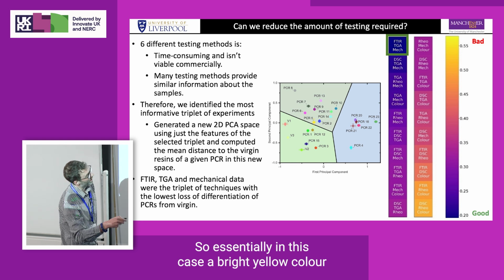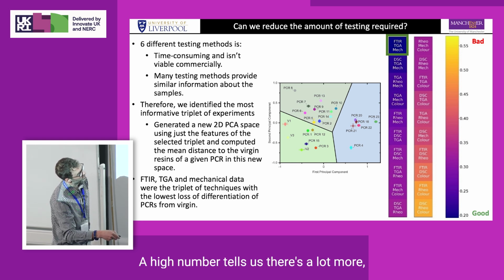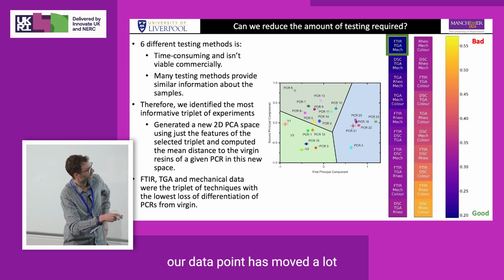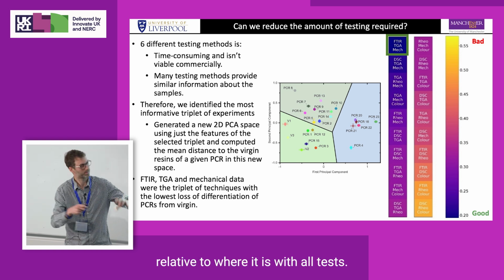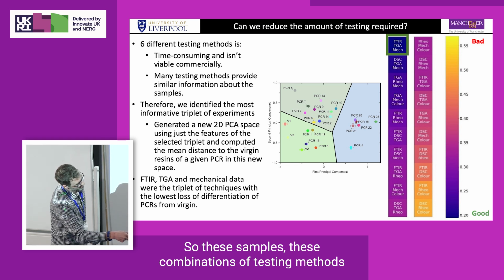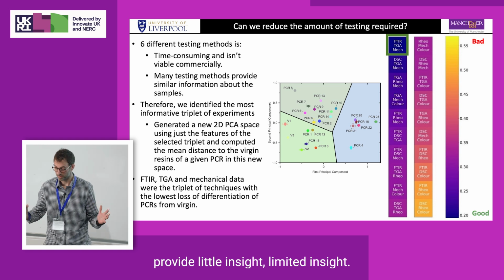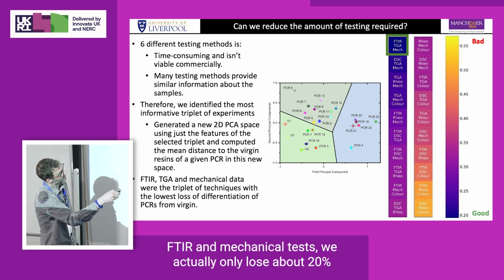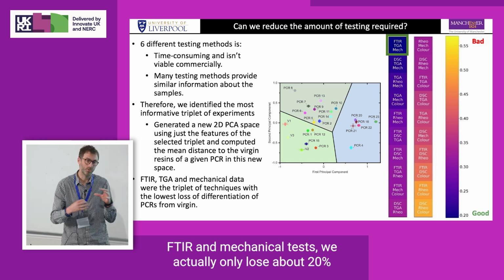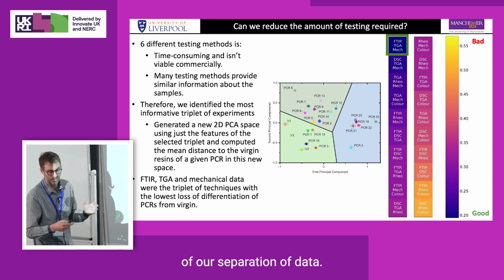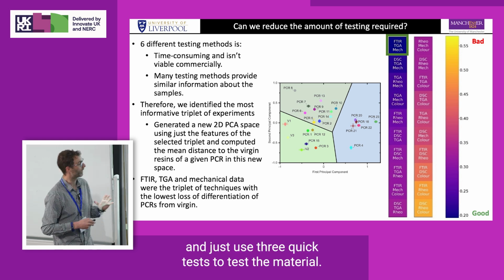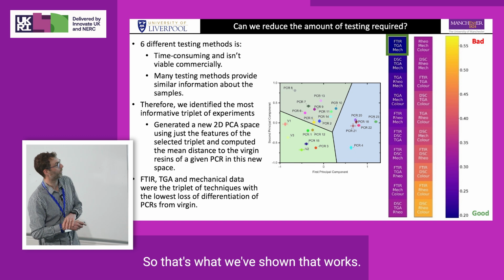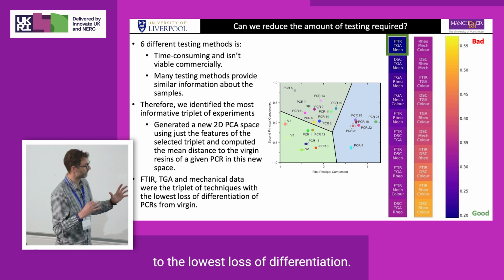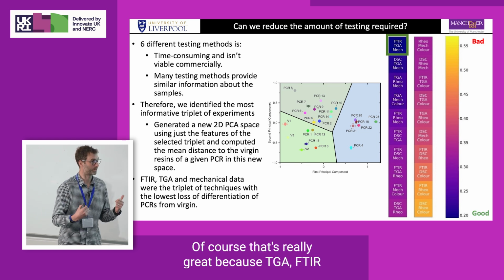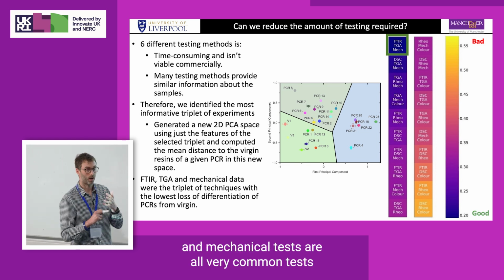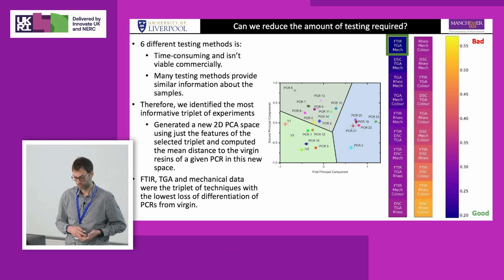So essentially, in this case, a bright yellow color tells us it's bad. A high number tells us our data point has moved a lot relative to where it is with all tests. So these combinations of testing methods provide little, limited insight, whereas actually if we take thermogravimetric analysis, FTIR and mechanical tests, we actually only lose about 20% of our separation of data. So we can really simplify and just use 3 quick tests to test the material. So that's what we've shown works. And these are the ones that lead to the lowest loss of differentiation. Of course, that's really great because TGA, FTIR, and mechanical tests are all very common tests that can be done in industry.